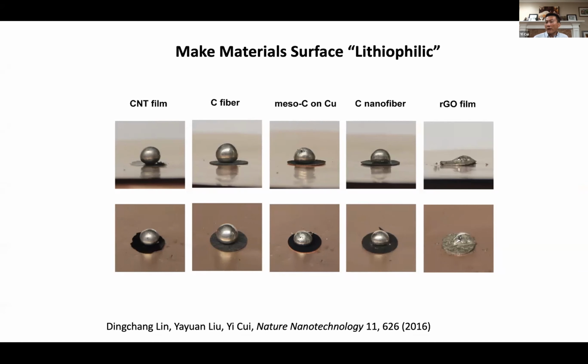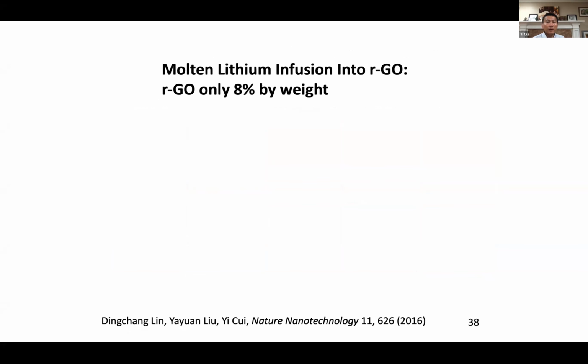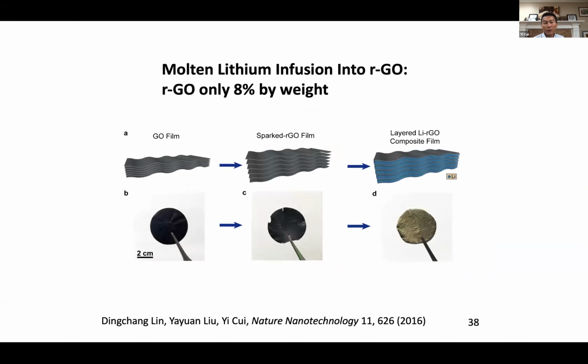The reason this can wet is that graphene oxide has a lot of polar functional groups that react with lithium metal. That's why I emphasize that depending on what type of carbon you have, the nucleation behavior could change and the wetting behavior could change. With polar functional groups right there, you can promote lithium metal wetting in the molten state. If it's a solid state, it would like to deposit and nucleate. So with very lightweight graphene oxide, 8% by weight, this host material is a very small amount. We could melt lithium and let it go in. And then once you strip lithium and deposit lithium, you have to deposit them back into the host.